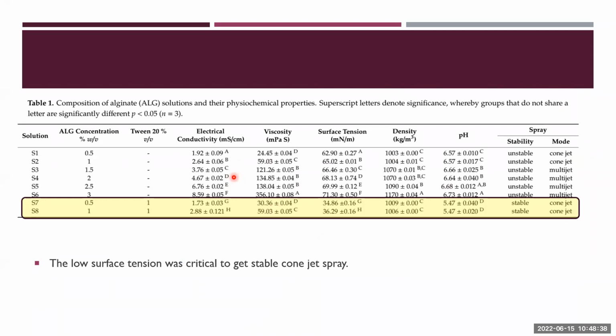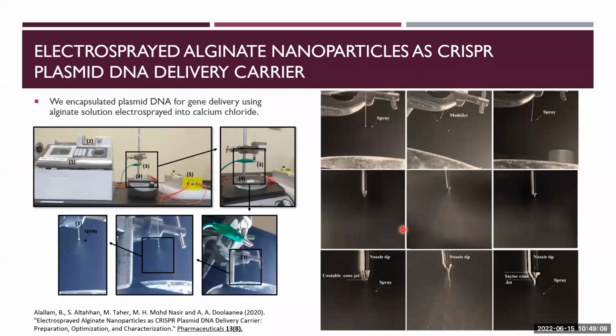So we have studied different combinations and concentrations of the polymer, adding surfactant, and we studied all these parameters of the solution, such as conductivity, viscosity, surface tension, density, and pH, until we got the suitable, stable cone jet that produces stable and reproducible particles. The good thing here is the reproducibility. Whenever you prepare the same solution and use the same setup, you will end up with almost the same size and the same parameters of the particles.